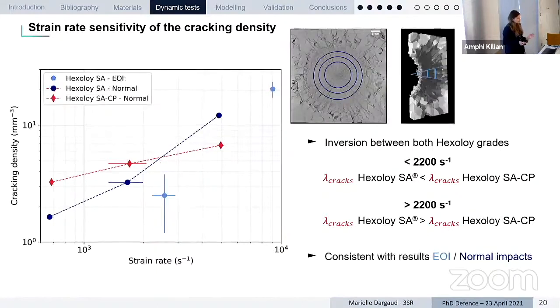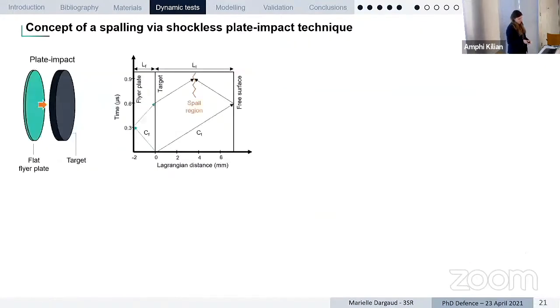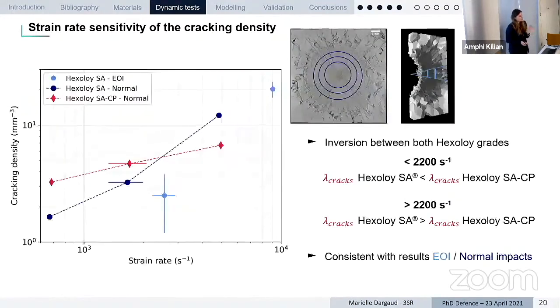If we add a few points for the Hexoloy SA in the edge-on impact configuration, we can see that the results are pretty close between the normal impact and the edge-on impact results. So here we have a quantification of the cracking density sensitivity to the loading rate.